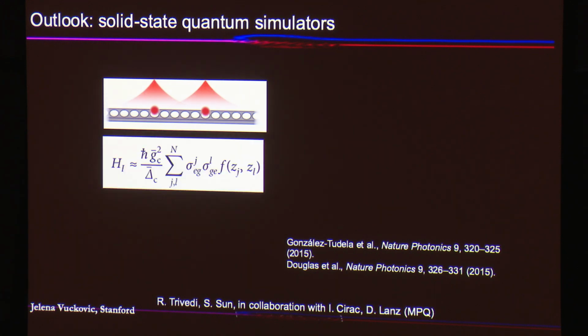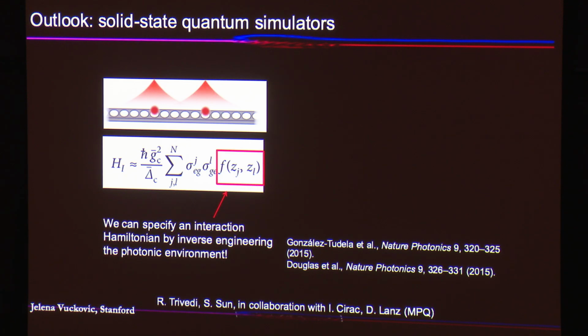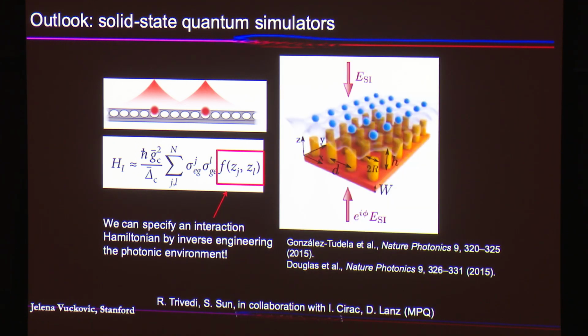And this idea has been around for several years, and Jeff Kimble here has been working on these solid-state simulators, as atom-based simulators, I'm sorry, but the same proposal, where the idea is to have kind of equivalent of optical lattice, atom array, but you couple it to some sort of photonic structure underneath, and that dispersion of the photonic structure on the mode pattern in the photonic structure would kind of control the interaction between different atoms in the array. And you can achieve also long-range interaction by starting with the structures that have low group velocity, high density of states. And again, people are trying to do that in atomic physics, most notably Jeff Kimble here.